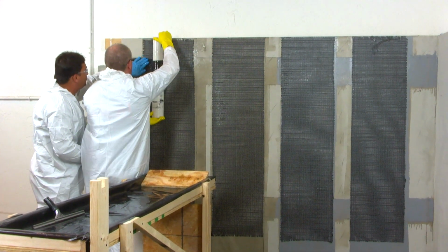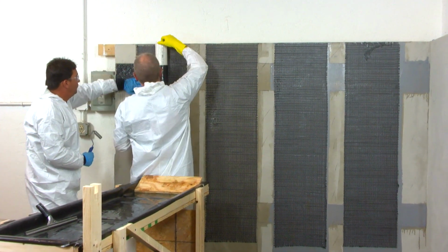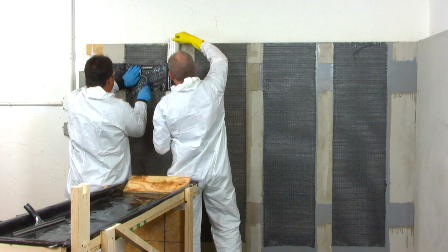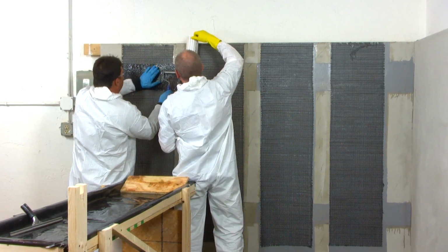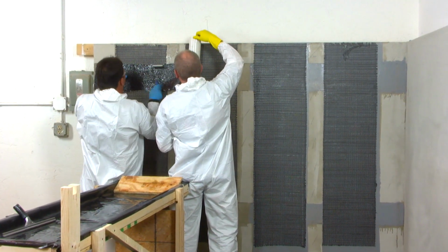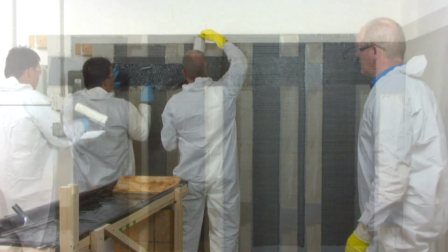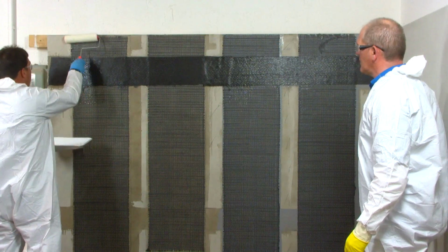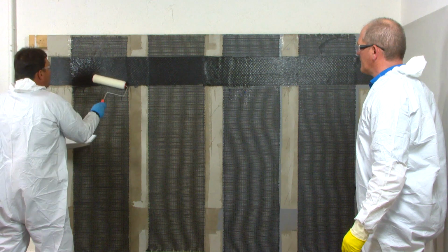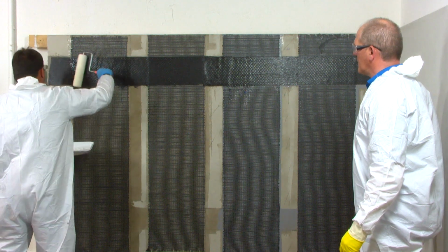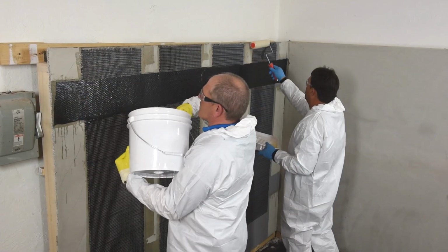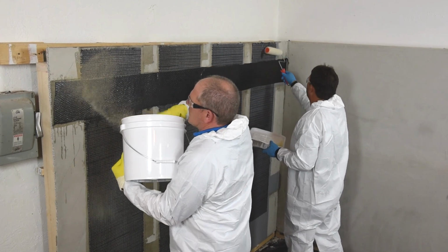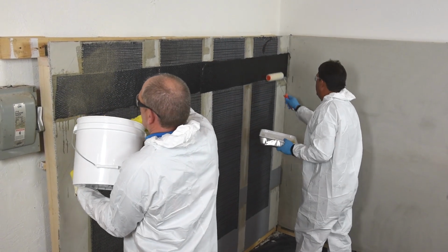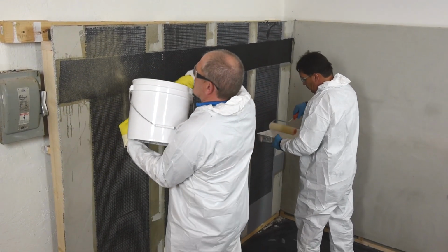If additional layers of carbon fiber fabric need to be overlapped, it is often more effective to do so immediately while the previous resin is still fresh. This ensures a better bond between layers. After several passes using a ribbed roller, another light coat of MapeWrap 21 is applied onto the surface. Immediately afterward, a saturating broadcast of clean dry quartz sand, 20 to 30 mesh in size, is applied to the surface.